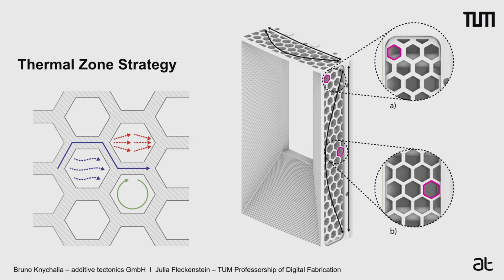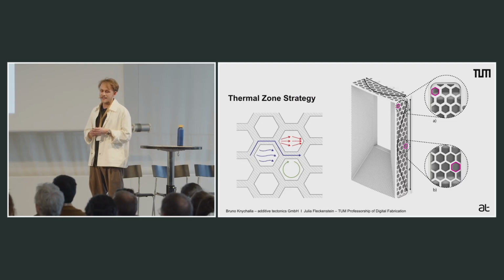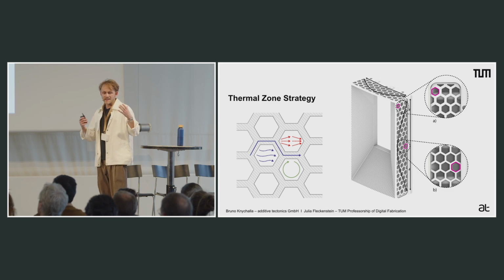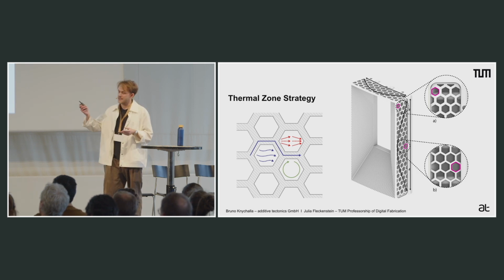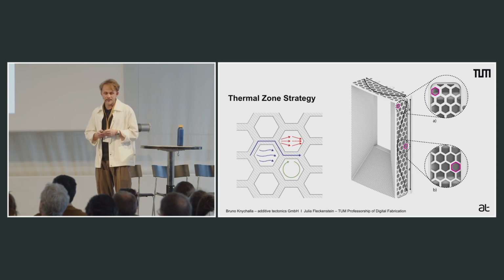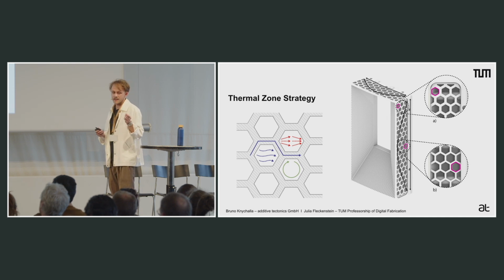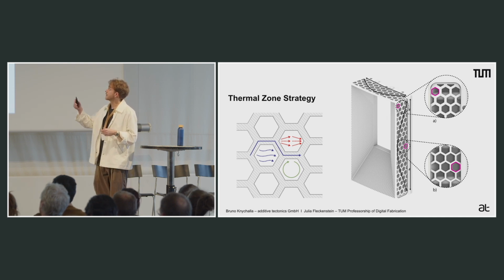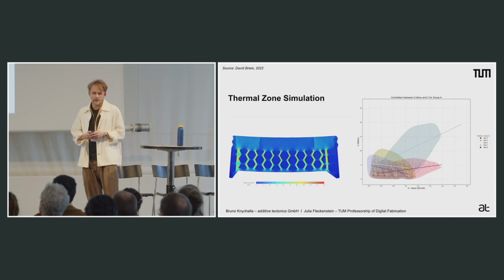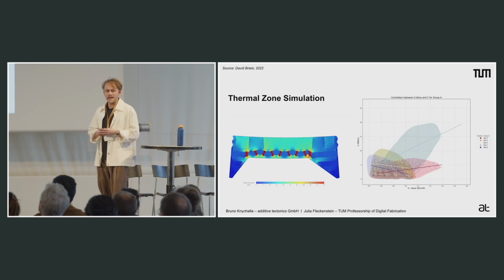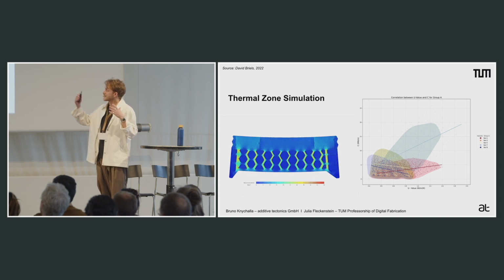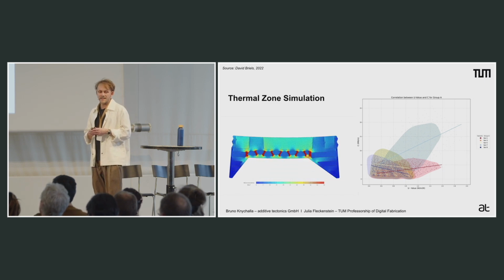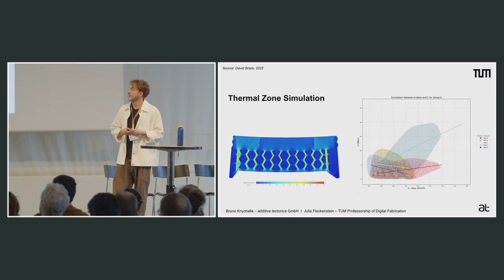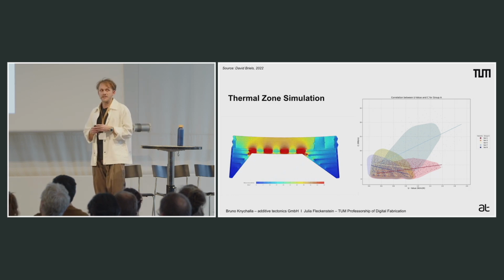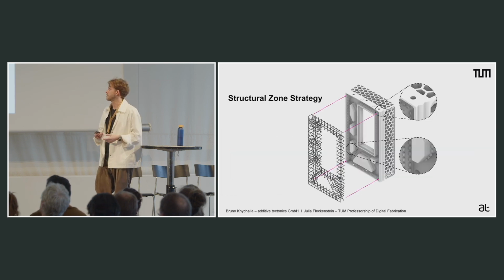For the thermal zone strategy, we analyzed different cell geometries for the thermal performance in 3 categories. Radiation you can see as red, convection in green, and heat flow in blue. The cells vary in size and thickness throughout each element and are thicker where more stress is expected. We did FEA analysis for heat transfer, and different cell families were compared, basically for the compressive strength and for the U value, and we chose a family of cells that would integrate nicely also with our fabrication parameters.